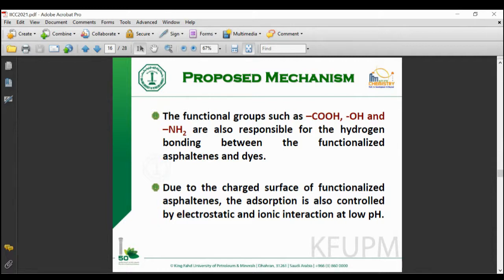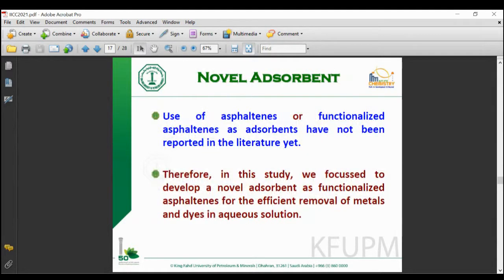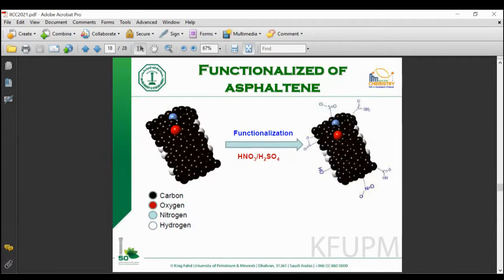They interact, and they afforded us more than 95% removal. Actually, more than 95%, sometimes 99% adsorption of the metal cations. We find out here, due to charged surface and other activities, the use of asphaltenes or functional asphaltenes as the adsorbent has not been reported before. Therefore, in this study, we focus to develop an adsorbent, and we have to look at the mostly used adsorbents for the metals and dyes.